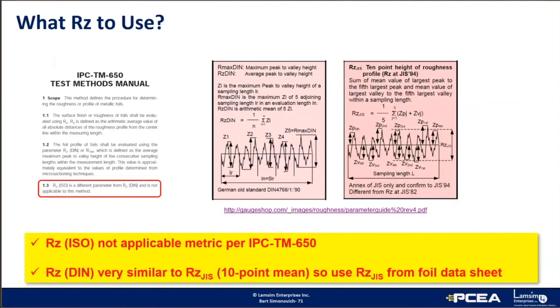TM650 recognizes RZ-DIN. It's similar, but instead of measuring the sum of the average of the five highest peaks and the five lowest valleys, it measures five peak-to-peak heights over a sample length and then averages them out.